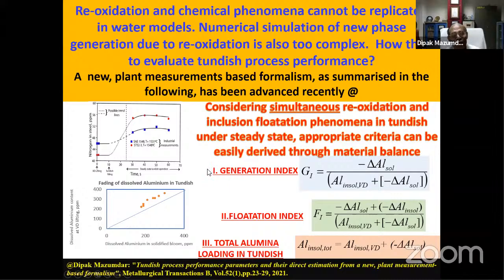Now, if you consider this process of alumina generation, particularly for aluminum killed steel, and carry out a simple high school level, 10th class material balance, you could very nicely find out three parameters. One is called the generation index, the other is called the flotation index, and the final one is the total alumina loading in the Tundish. This is the generation of inclusion, because whatever dissolved aluminum has faded, this delta meaning change, has manifested in alumina formation.